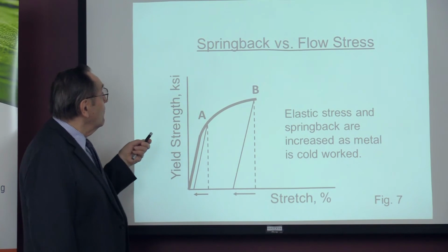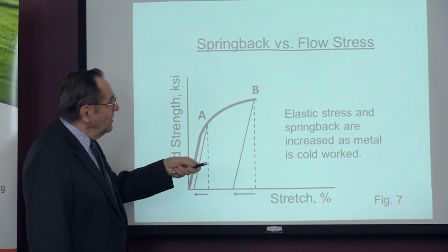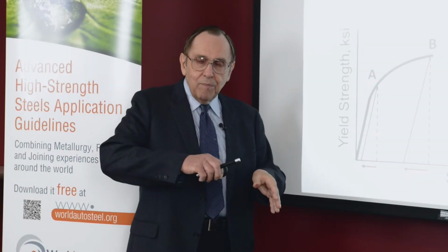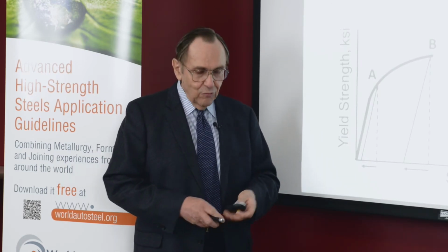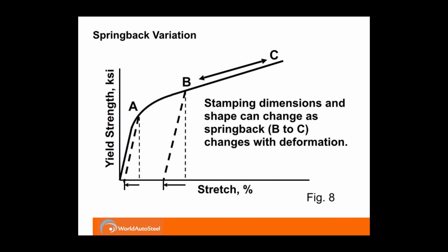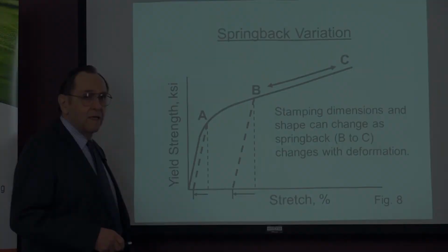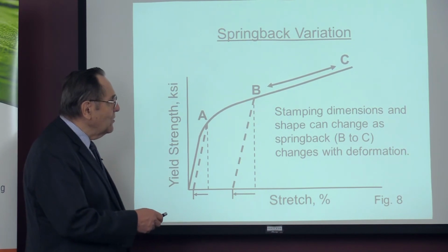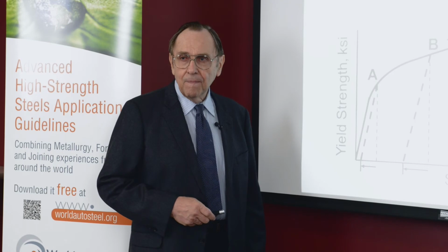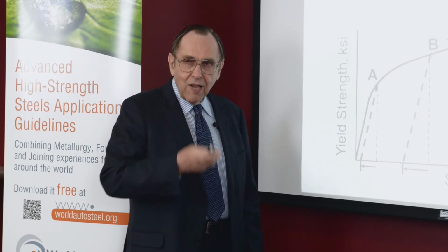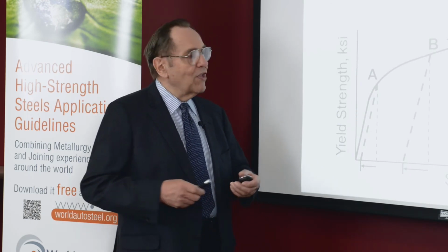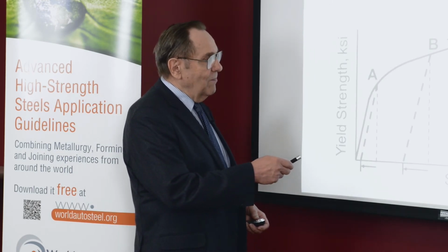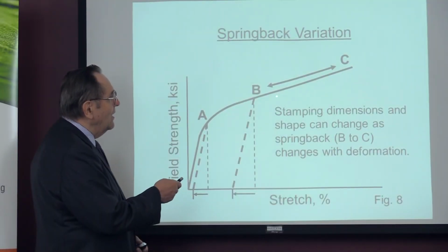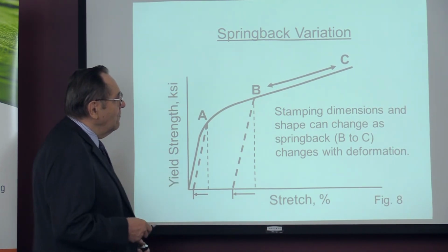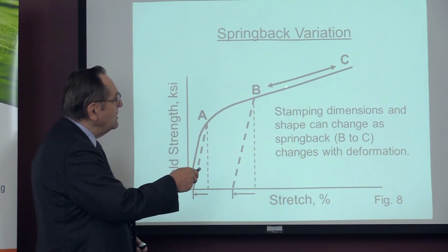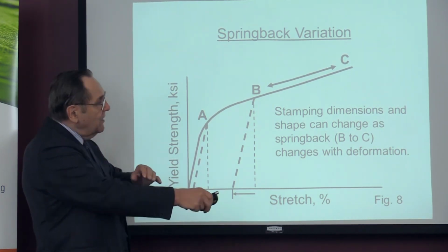So part of the stamping that maybe over here has a certain amount, more over here, less over here. And now you have a distribution of springback, which then has to interact until it reaches a balanced condition. Well, that would be nice if everybody had A to B, okay? It would be very nice. However, there are things where you have stampings going up to C. You might have a strain gradient, which goes up or down as changes in the die or changes in lubrication or the temperature or the speed or whatever. And so you're bouncing back and forth up in here. And this is also a reason where you get this deformation from a gradient, which is a sharp localization of deformation, often on a character line or something like that.